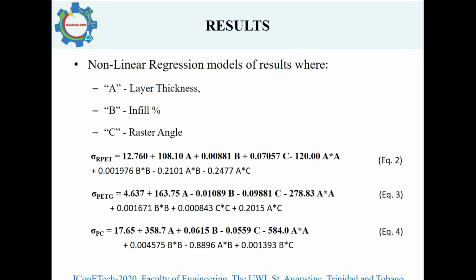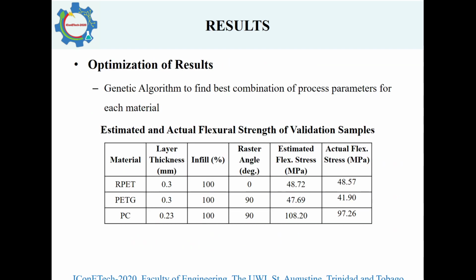These equations fed directly into the genetic algorithm as the objective function being solved. The genetic algorithm, or GA, searched for the print parameters to produce the highest flexural strength, and using those values, which can be seen in the table, validation samples were printed and tested. From the table, it can be observed that the actual stress values from the validation experiments were lower than that predicted by the genetic algorithm. The RPET strengths were fairly similar, but the PETG and polycarbonate PC had a slightly larger deviation.